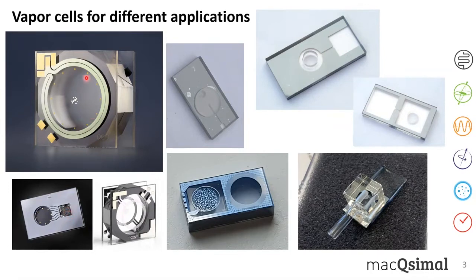But most of the work we did here at CSEM is based on the fabrication with rubidium azide. Here you see one example of a cell that is used in the OPMs. This is a cell with two different chambers that are separated by a small narrow trench. And here you see a lot of rubidium that condensates in this filling chamber, but there's nothing in the science chamber, which is very good. So we want to avoid rubidium sitting on the glass, because we have to go through with a laser to probe the rubidium atoms.